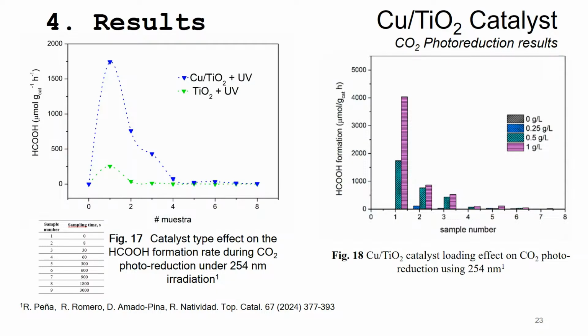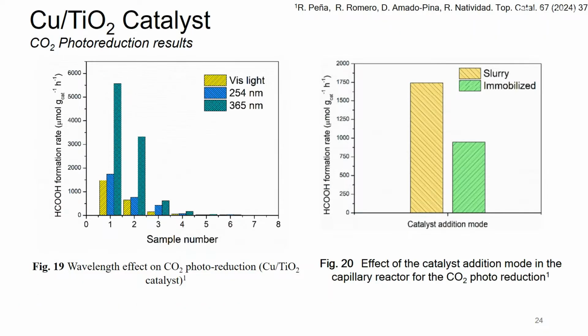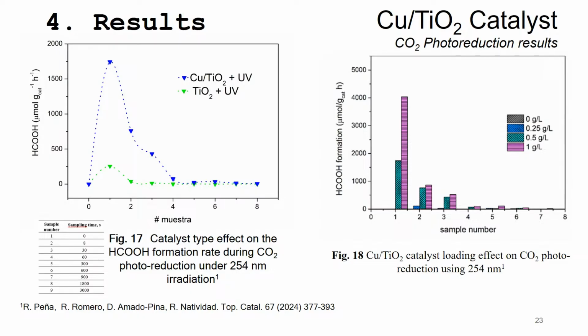Here are the results that we obtained in the production of formic acid. Here is for copper over titanium dioxide with UV light. You can observe here the effect of copper, which was pretty good. Here, for those who are starting to do your studies in photocatalysis, the catalyst loading is a very important variable. In photocatalysis, more doesn't mean better. In this case, it did, but why not?